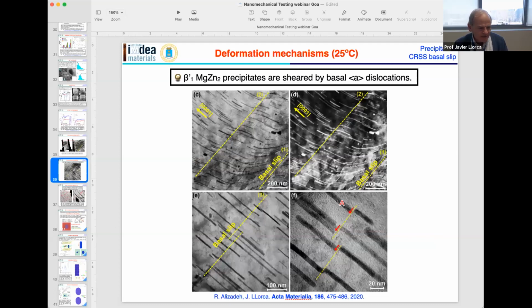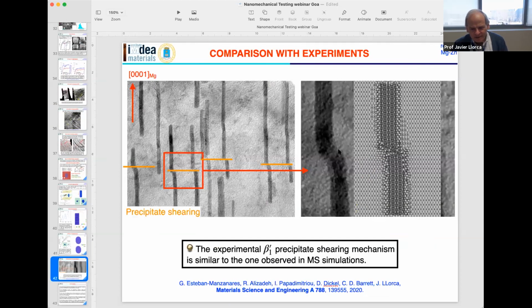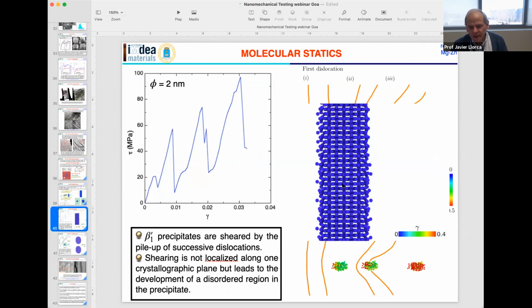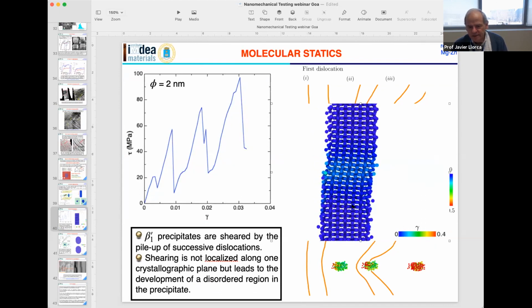But when you go to higher magnification, you really see that this shearing of the precipitate is not through a crystallographic plane. This is when we decided to do the MD simulations. In the MD simulation, we saw an Orowan loop, another Orowan loop, but finally the dislocation was able to go through. And as you can see here, shearing does not take place through a crystallographic plane. You are piling up dislocations, the stresses are higher and higher, and there is a point at which you create a region in the precipitate that is completely disordered. I guess this will eventually happen in any precipitate: if you pile up enough dislocations in front of it, the stresses at the leading dislocation will be so high that they will destroy the lattice of the precipitate.